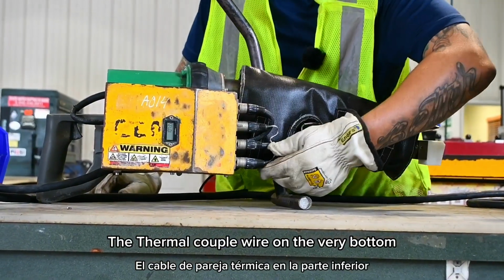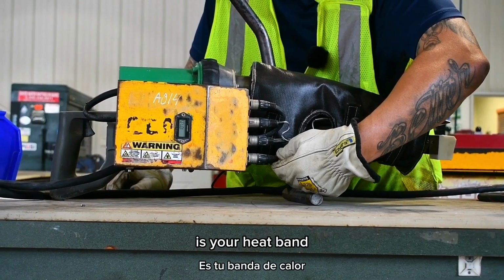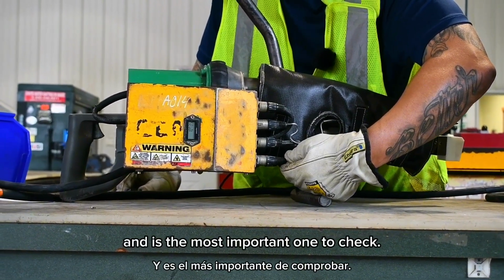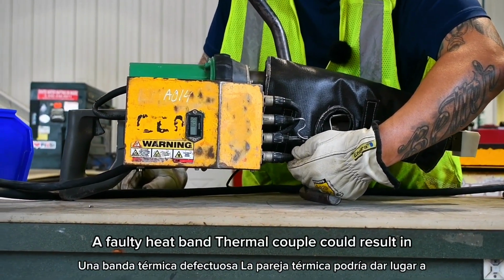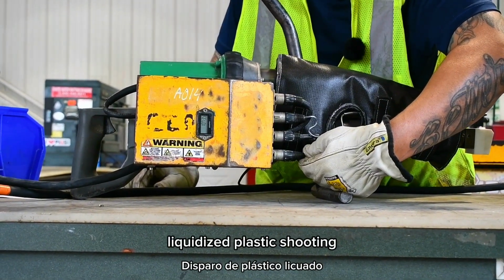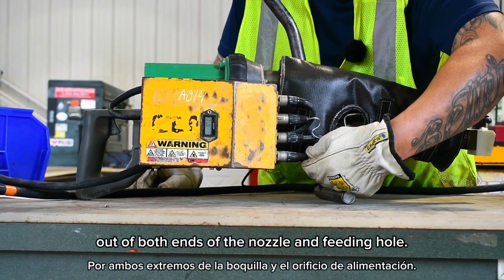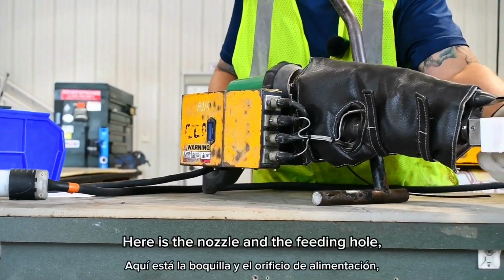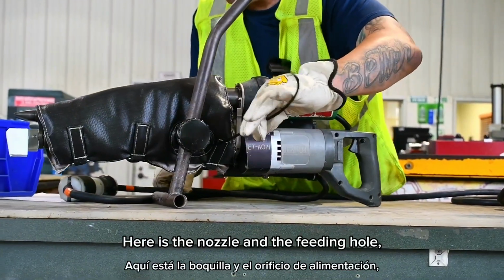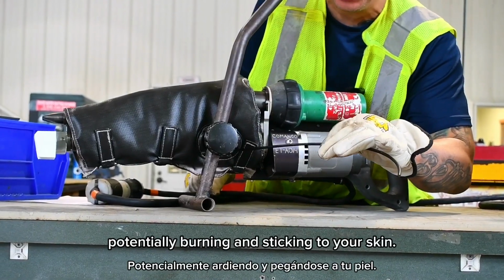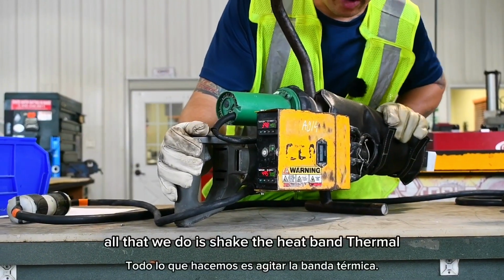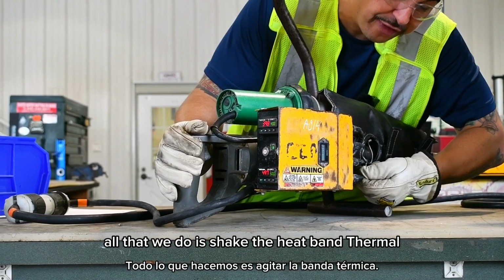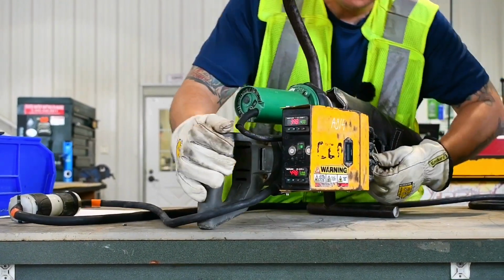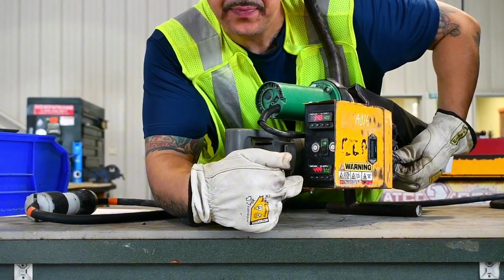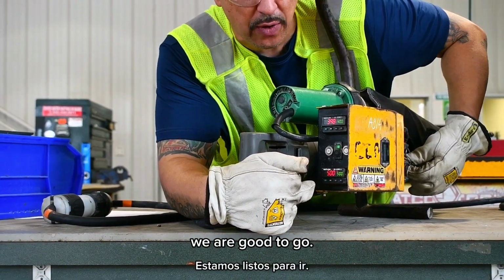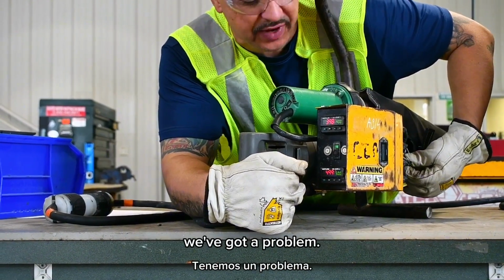The thermocouple wire on the very bottom is your heat band and is the most important one to check. A faulty heat band thermocouple could result in liquidized plastic shooting out of both ends of the nozzle and feeding hole, potentially burning and sticking to your skin. With that being said, all that we do is shake the heat band thermocouple, both ends, and we make sure our number is stable. If our number is stable, we are good to go. If it's jumping around all over the place, we've got a problem.